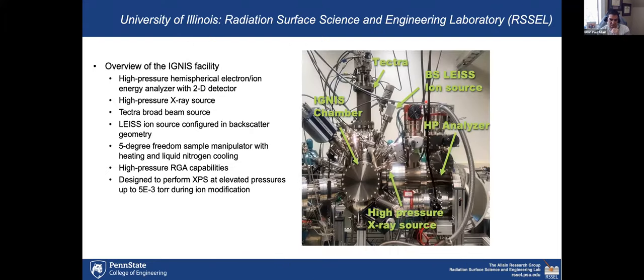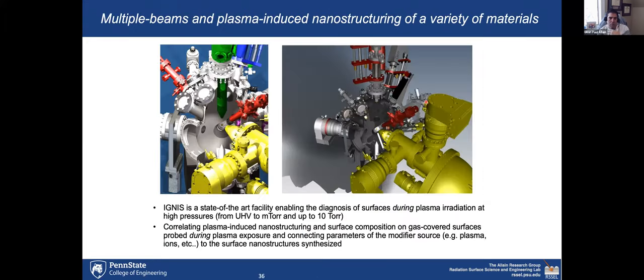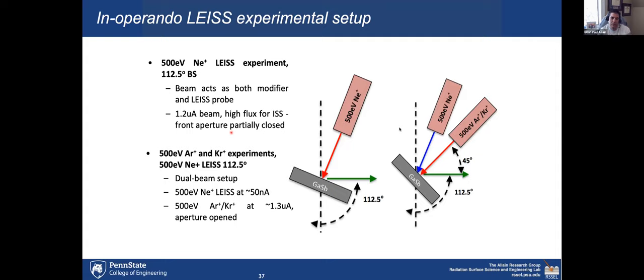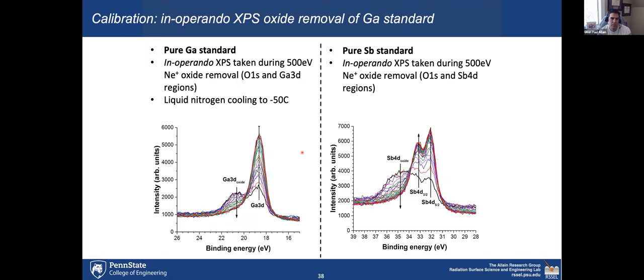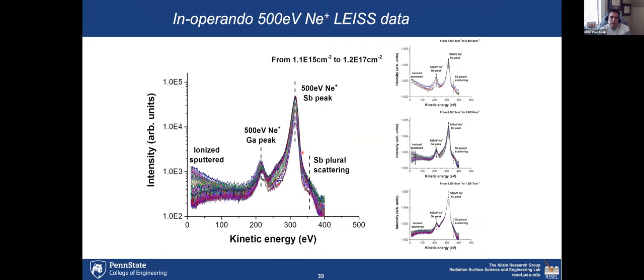Further studies were done in our facility, the Ignis facility back at Illinois. We're still running that facility now, and it is equipped with all of these techniques in situ and enables us to watch how these surfaces evolve. For this particular study on the nanopatterns, we combined a number of different experiments that not only induced the nanopatterning, but we also conducted LEIS in situ and during the radiation. I'm not going to get into all the standardization that we did using XPS and low energy ion scattering, but I'll get to the spectra.